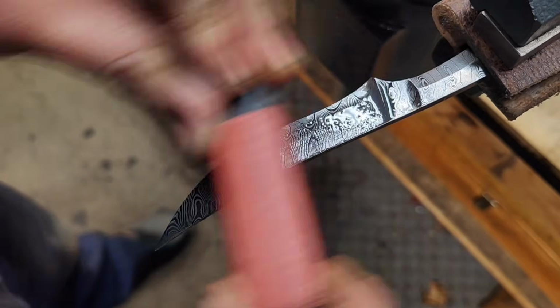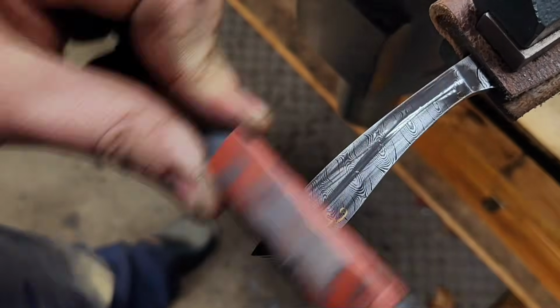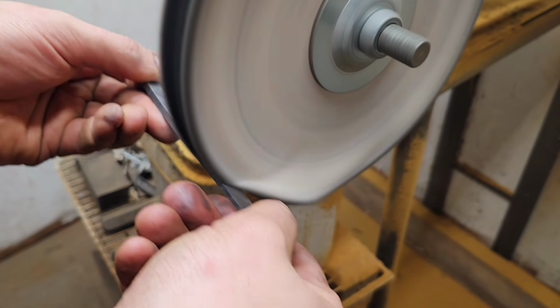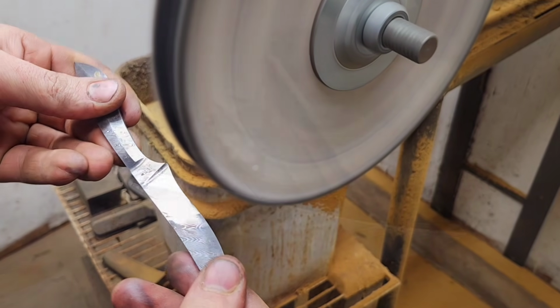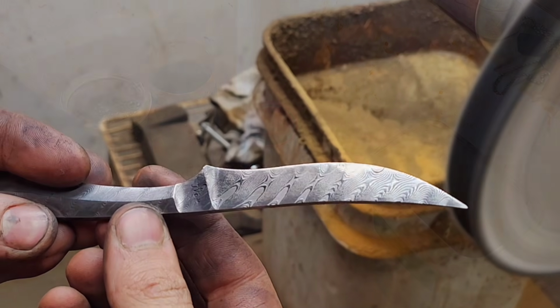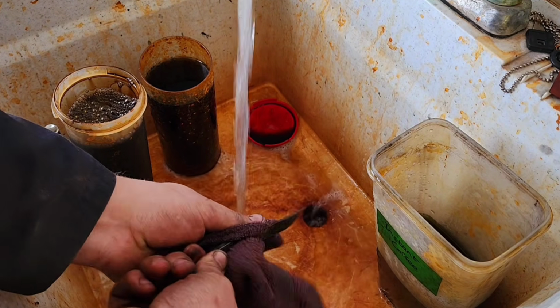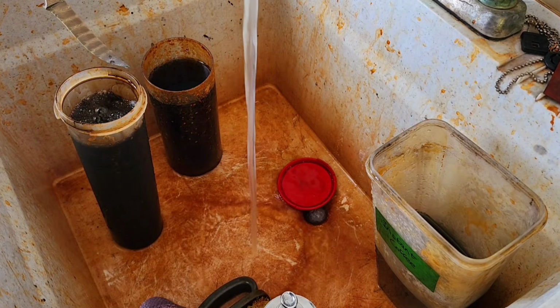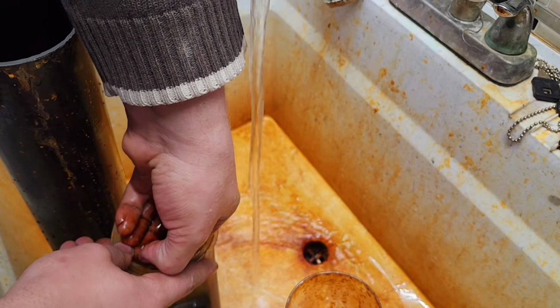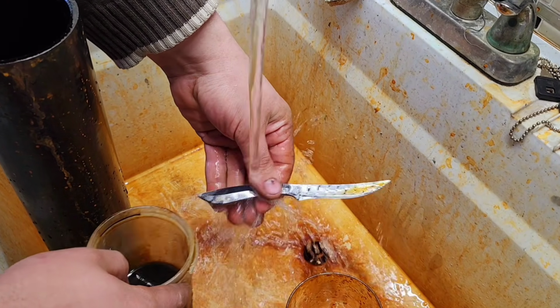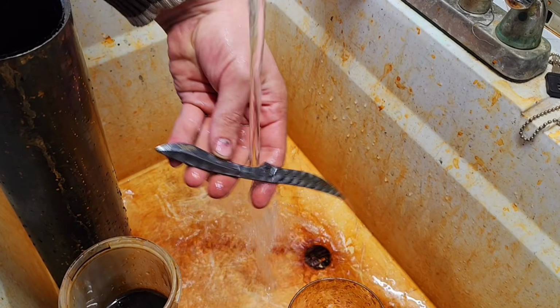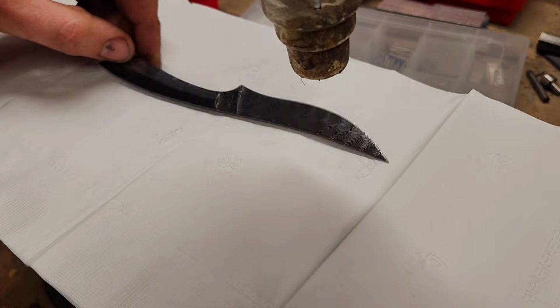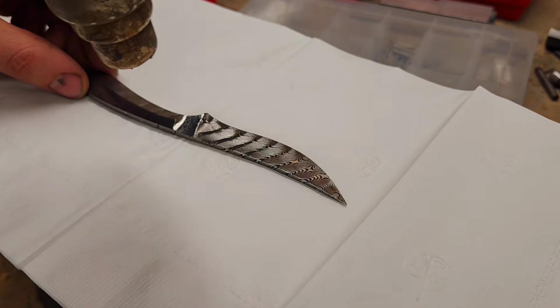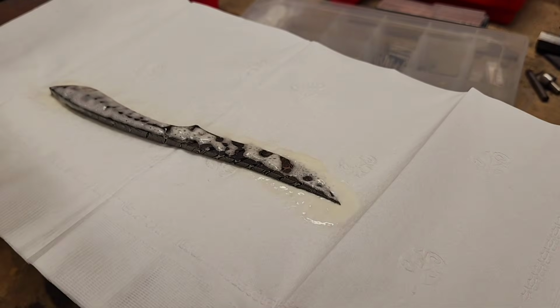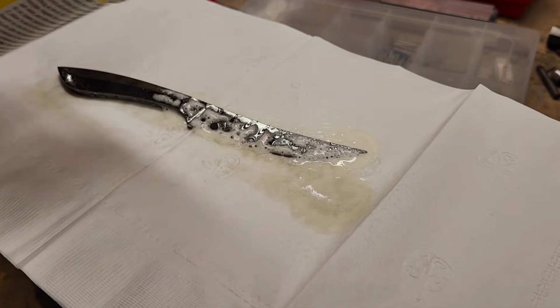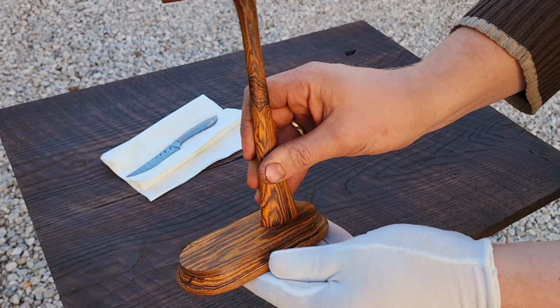And we're going to move on to hand sanding the blade and the handle. So all the Damascus parts, everything that's Damascus must be hand sanded to 1200 grit. And then we polish. Make sure it's good and shiny. And now we're going to wash it good with a cloth. And we're going to put it in some instant coffee. The instant coffee will really make the 1084, that manganese steel, very dark, while yet still keeping the 15N20, that nickel steel, very shiny. Spritz some gun oil on there. And we're finished. Let's assemble the stand.